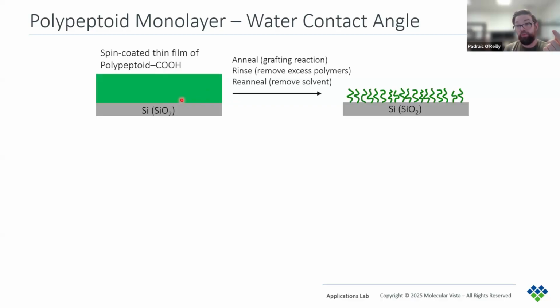The monolayer is formed by spin coating a thin film, annealing it to produce the grafting reaction. This is where the molecule will covalently bind to the silicon. Rinse the excess film away with solvent and then anneal again to remove this solvent.